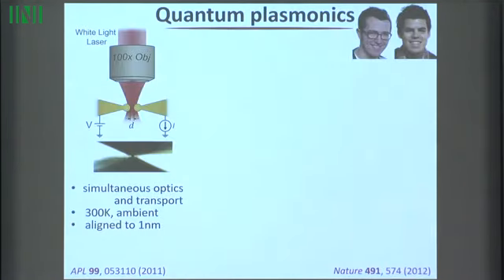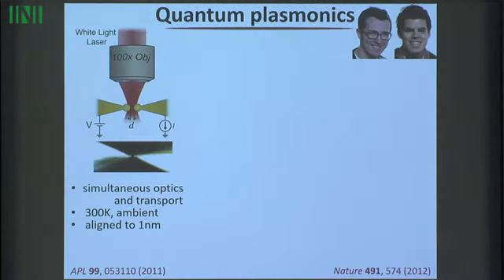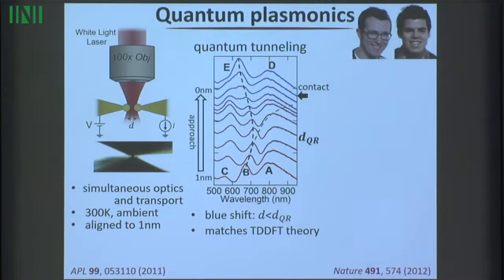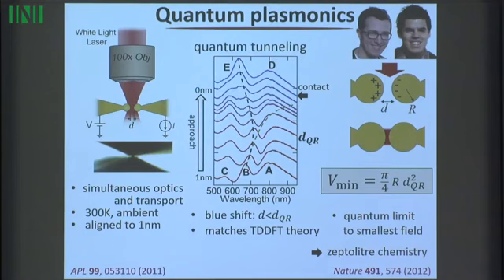And we did that a few years ago. So we actually had two tips. We bring them close together. We measure when the quantum mechanical tunneling happens. We look at the colors here. And about this point here, when the gap is about 0.4 nanometers, we start to see this quantum mechanical tunneling effect here. So basically it tells us we can only confine light a certain amount because quantum mechanics will actually take over and actually discharge the very large optical fields we're creating there.